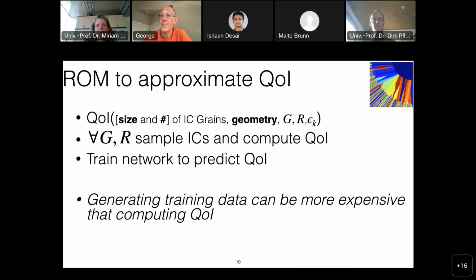The statistics are given. But in reality, you can imagine one layer: when you do a layer, it will create this microstructure. The powder will go on top of that and will start melting. So one main way they're coupled is that the statistics of the grain microstructure affect the next melt pool on top of the layer. So in some sense, you have to do them sequentially, and the only thing that will change is that this substrate is not random, but comes from previous simulations. Okay, it's in the generation of these seeds for the grains. Correct. That is a fully coupled process, in the simulations and the neural networks.